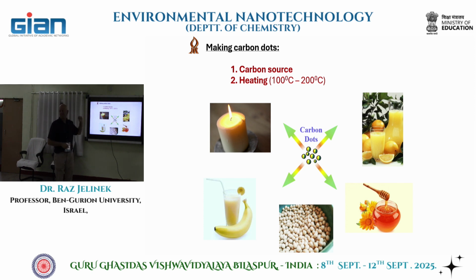But this is not carbon dots. Here, it's very gentle. You heat to a relatively low temperature, 100, 200 degrees, for a few hours, and then you get carbon dots. That's how you get them.